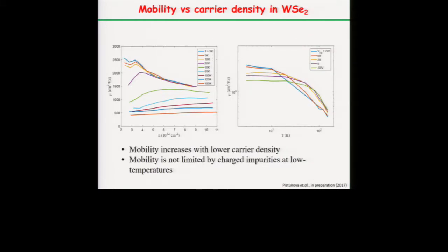Interestingly enough, even when we are reducing the carrier density, mobility is going up. So we are not seeing any charge impurity scattering dominated transport. That usually happens in MoS2. So for MoS2, you cannot go lower in density, because mobility really reduces a lot, as I will show in one of the slides. In tungsten selenide, on the other hand, the material is better quality, and mobility keeps increasing.